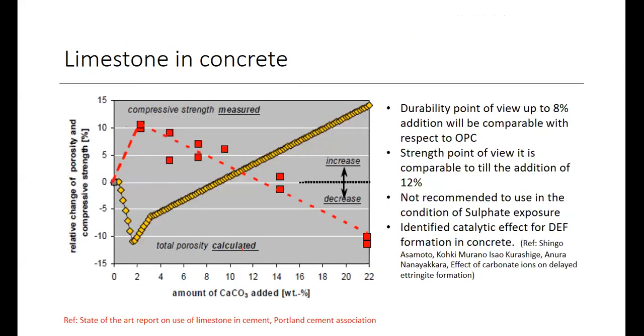Okay, limestone. Limestone also, I have taken from this research. Here you can see the change of porosity and the compressive strength as a percentage. The zero means conventional OPC, and here is the amount of calcium carbonate, limestone addition. You can see up to about 2% addition of limestone, it even improves the strength, even up to 10%. And it reduces porosity. Reduction of porosity is a plus sign for improvement of durability. So it's good to improve the durability.